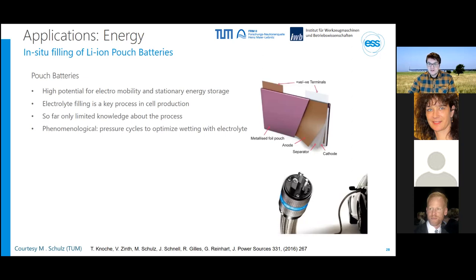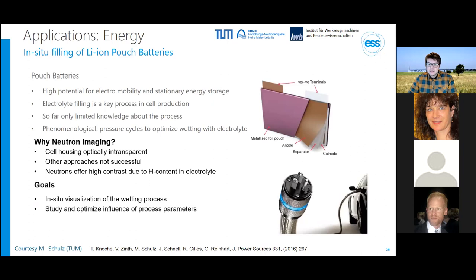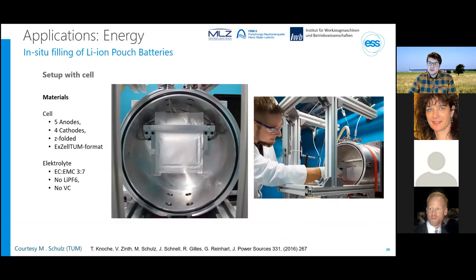And while the actual filling process takes only a few seconds, battery manufacturers often wait several hours to ensure the liquid is fully absorbed in the pores of the electrode stack. The colleagues from the Technical University of Munich at their neutron source have applied neutron imaging to study this filling process under different process parameters, as the hydrogen of the electrolyte is highly visible for neutrons, while the housing is almost transparent. Here you can see the experimental setup that allowed them to visualize the soaking behavior of the electrolyte liquid inside.